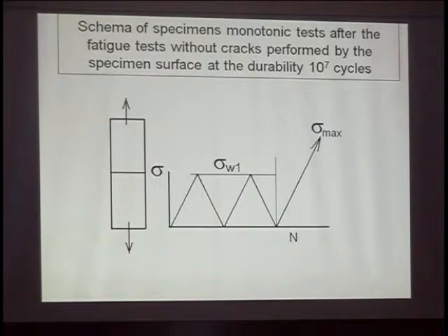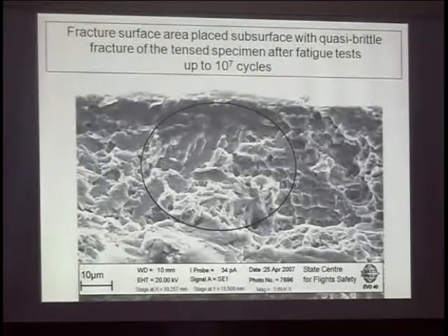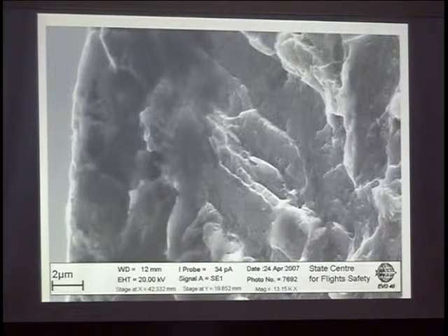Very interesting for me, first of all. I think it will be interesting for you to hear results about opening specimens that had not cracked during the test, and we tried to see whether inside the material there really exists an area of predominant material cracking or origination. You can see that it was so. We opened the specimen and we saw that there exists a very small area with a reorganized manner of cracking, because you know that for slow crack speed, material cracking exists with very good, very clearly determined dimples. But in this area you can see approximately quasi-brittle fracture because of the organization regime subsurface.